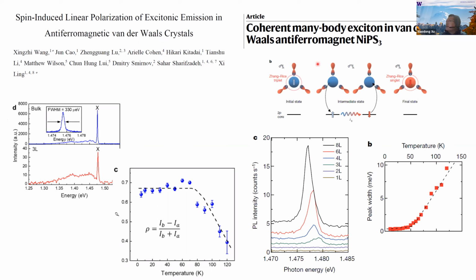There's another work from a group in Korea. In this work, they also observe narrow exciton luminescence as a function of layer thickness. They measure all the way down to the trilayer, and they didn't observe luminescence from the bilayer and the monolayer. They also measure the peak linewidth versus temperature, just as I showed you, and the linewidth broadens as the temperature increases. An interesting point made by this paper is that they attribute this exciton to a many-body exciton, a Zhang-Rice singlet. The evidence mainly comes from recent X-ray scattering measurements, which is beyond what I can understand, but if you're interested in this topic, you should check out this paper.